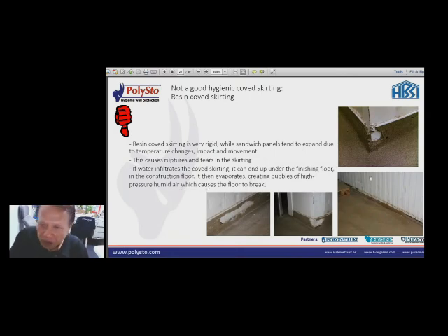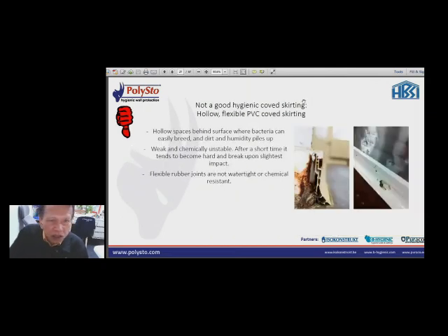Okay, so here you could see it in these pictures. Not a good hygienic cove skirting. Hollow, flexible PVC cove skirting. As you could see here, it uses a PVC which already is deteriorated. For this one, it's hollow, then eventually it will crack. Hollow spaces behind the surface where bacteria can easily breed, and dirt and humidity pile up. Weak and chemically unstable. After a short time, it tends to become hard and break upon slightest impact.